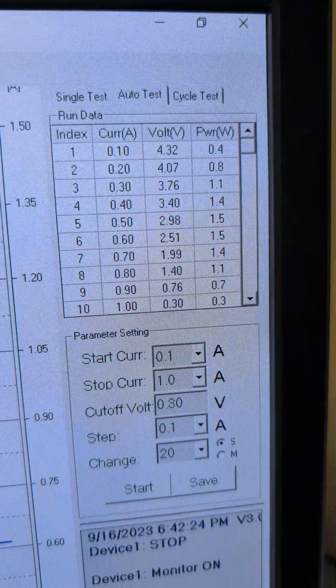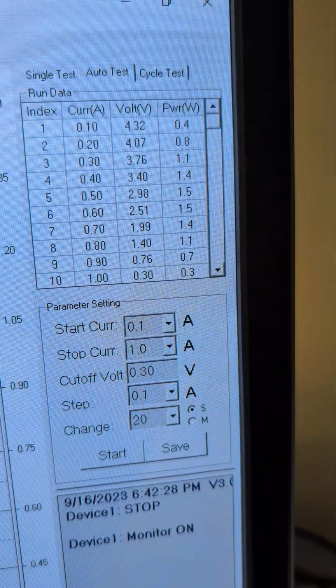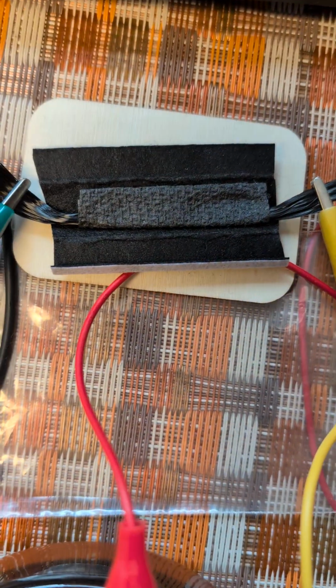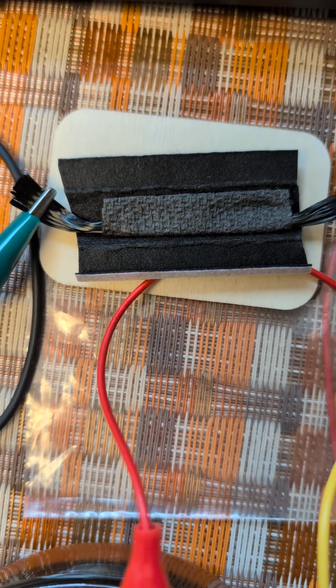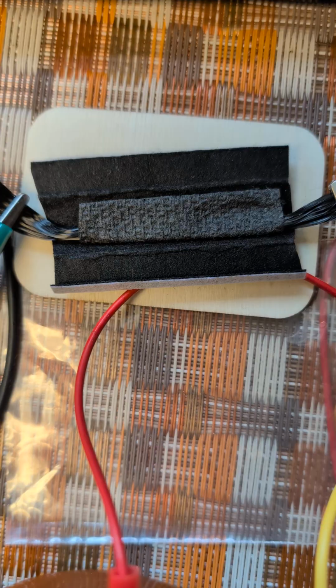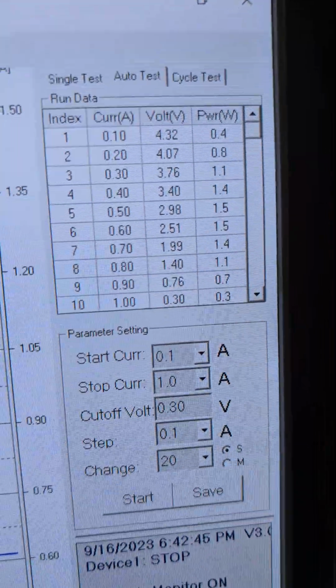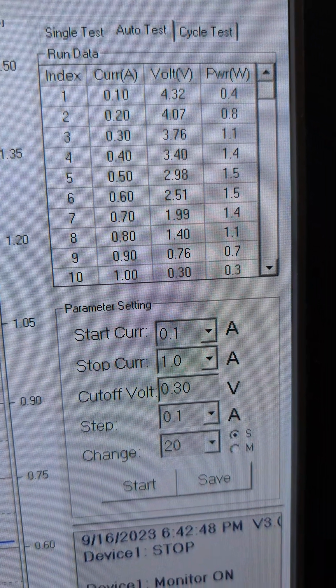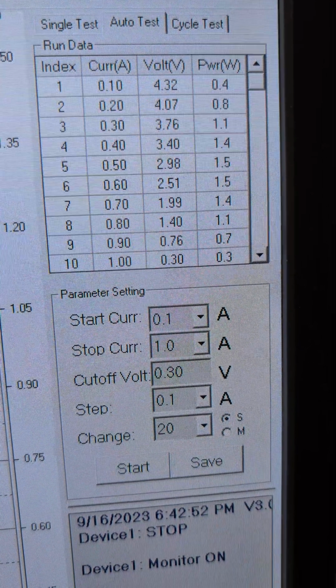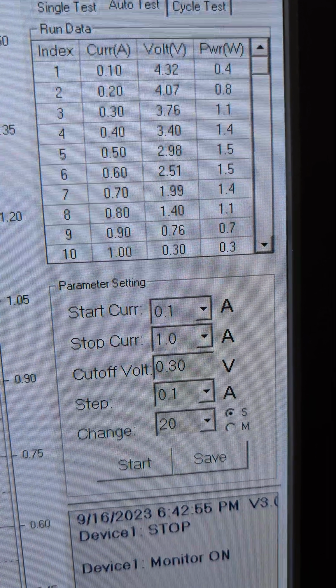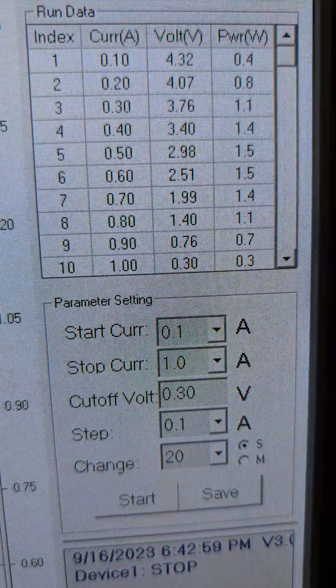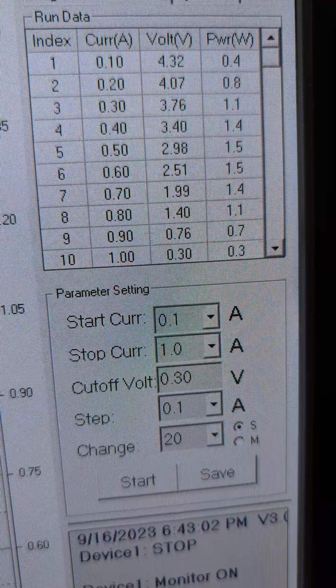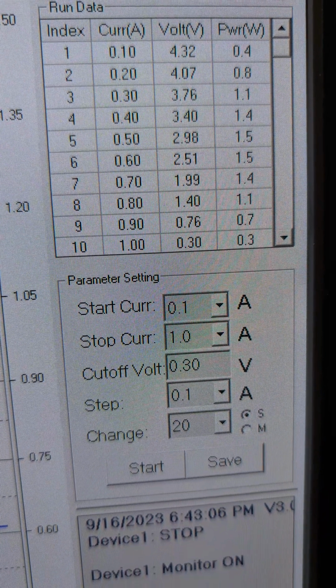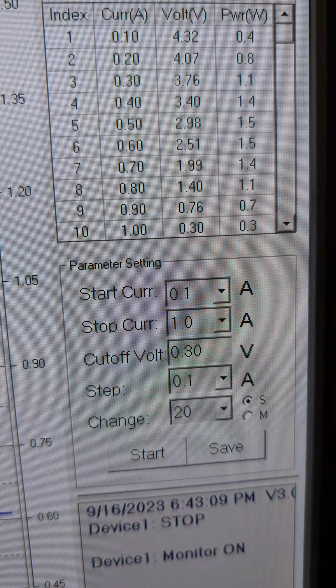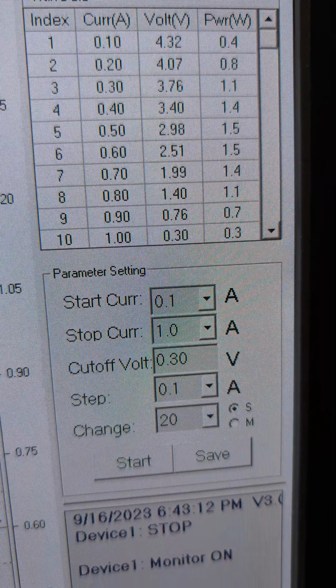And you can see here a run, which is this material shown. I did not seal it. We're just doing preliminary studies. And we got some good numbers, really. There are the numbers, index 1 through 10, going from 0.1 up to 1.00, 20-second intervals. There are the voltage drops, and then there's the power on the right in watts. So you can see we're doing maximum power output at index 5 to 6. That's about a half an amp, 500 milliamps. And then it drops down after that.